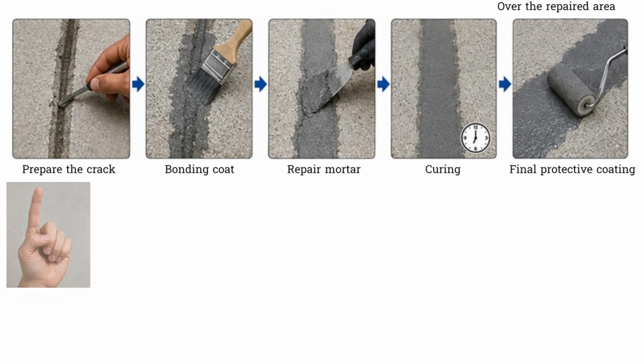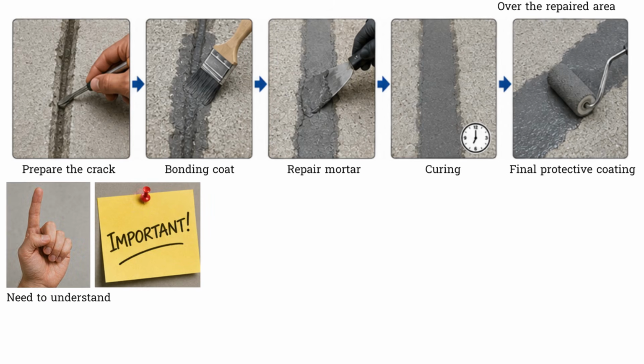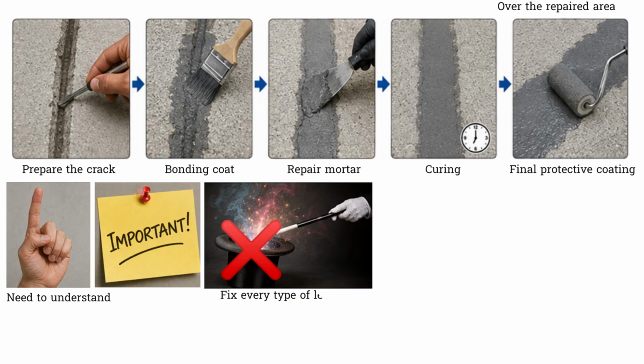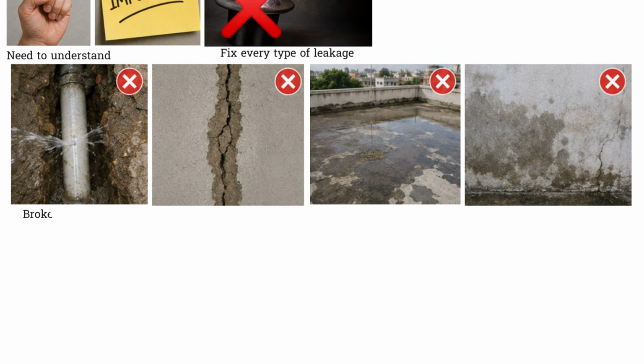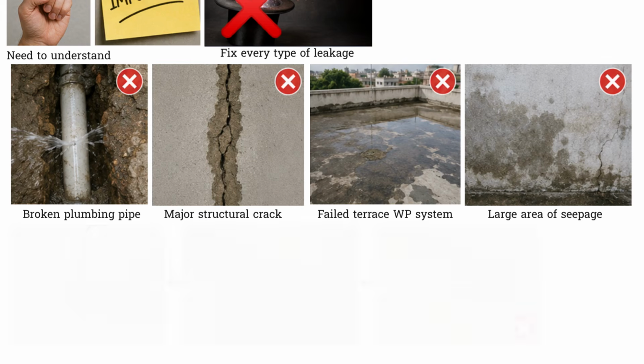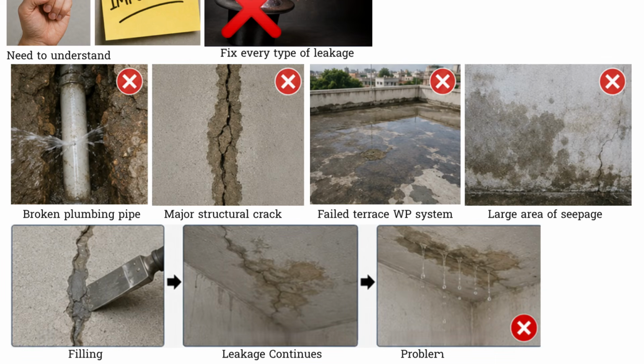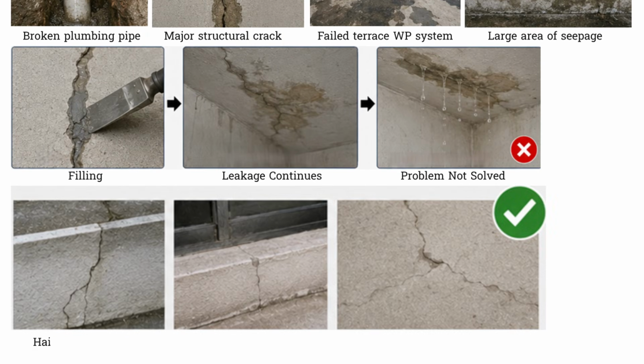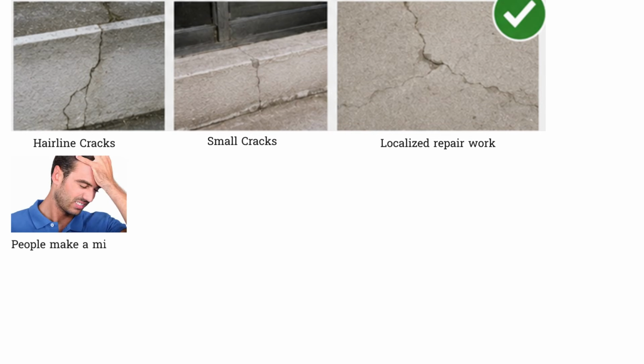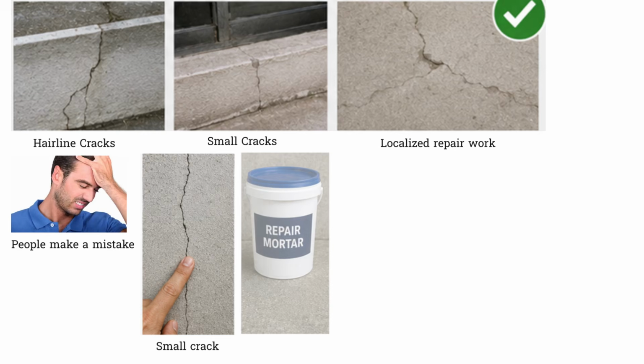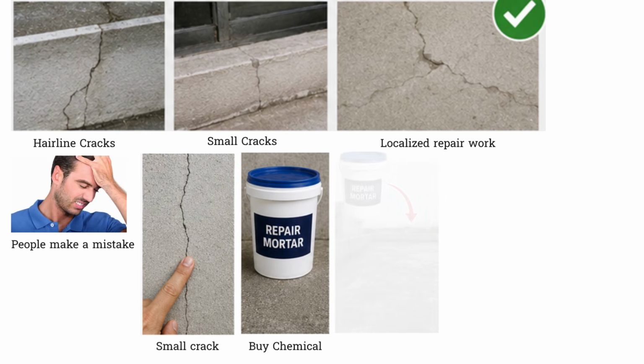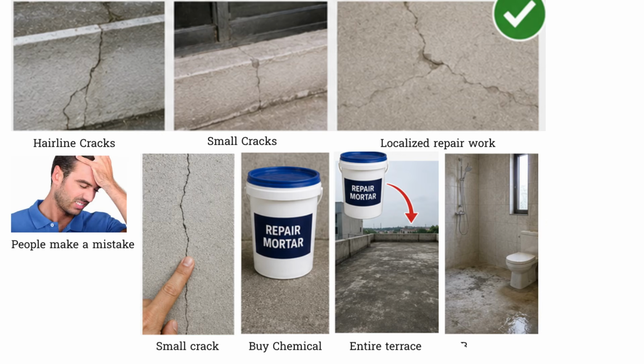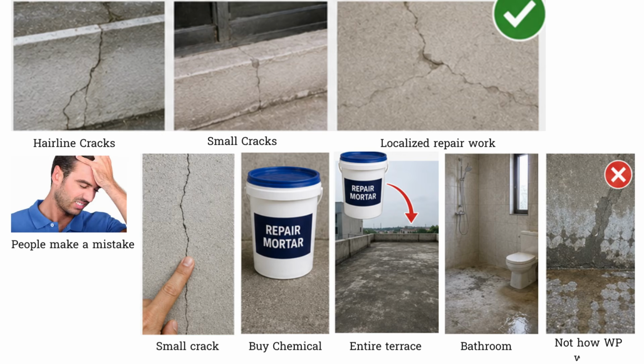But now, there is something very important you need to understand. This is not a magic chemical that can fix every type of leakage. If your leakage is caused by a broken plumbing pipe, a major structural crack, a failed terrace waterproofing system, or a large area of seepage, simply filling the visible crack may not solve the actual problem. This type of product is much more interesting for small localized repair work. And this is where many people make a mistake. They see a small crack, they buy a repair chemical, and they assume that the same product can be used to waterproof an entire terrace or bathroom. That's not how the waterproofing works.